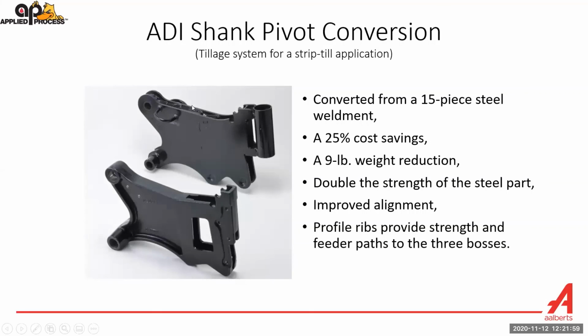agricultural component that was converted from a steel weldment, 15 pieces, to a 1-piece ductile iron casting that was then Aust-tempered. Again, look at the aesthetic difference between these two components. The welded component is on the top, the casting is on the bottom. So it was a 25% cost savings, a 9-pound weight reduction, and an improvement in strength, alignment, and everything else. So there was a lot of advantages to doing this conversion.